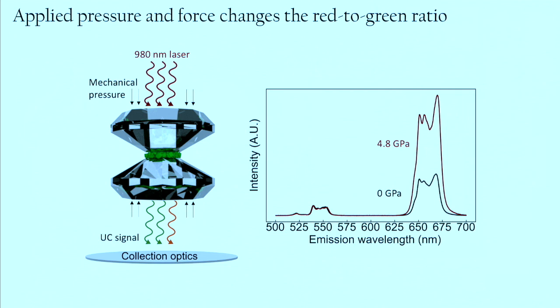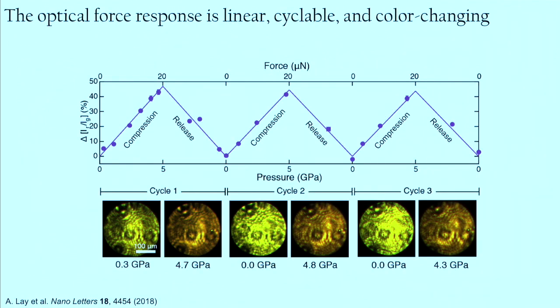And basically that ratiometric change, so looking at the red to green ratio, gives us a readout of what the force is. So here we're looking at the red to green ratio change. You can see it's linear with compression and with release. And it gives rise to, in this case, a yellow to orange color change. We can kind of tune the color change that we want based upon the forces that we think will be exerted by the system.